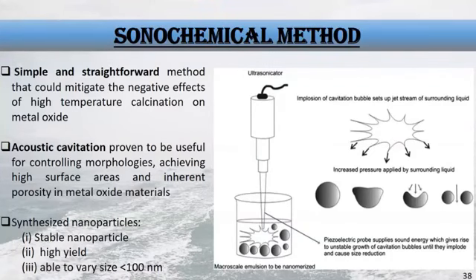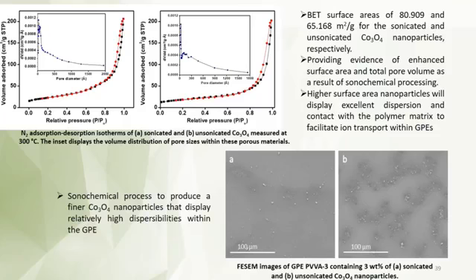And we consider here the acoustic cavitation, where the bubble is produced and the collapse of the bubble will give us synthesized nanoparticles with unique properties, like stable nanoparticles, high yield, and the ability to vary the size of the nanoparticles below 100 nanometer. And then the BET surface area also shows that the sonicated nanoparticles will have a higher surface area. So this is the evidence that it will display excellent dispersion and contact in the polymer matrix.